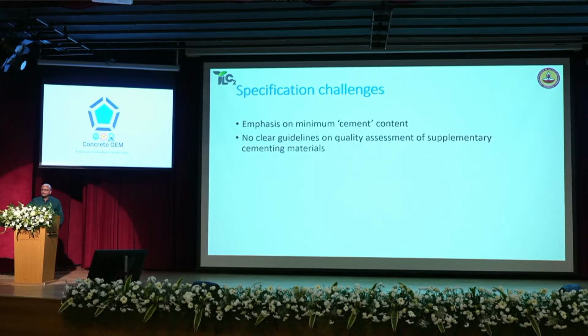There is no clear guideline on quality assessment of SCM, supplementary cementing materials. That is one of the problems why people have not been able to adopt SCMs as much as they should be, because very often the fly ashes that get supplied to ready-mix concrete do not have the right quality. And oftentimes the people who are supplying the fly ash do not ensure that the quality and the consistency of this fly ash is maintained from batch to batch. If you go to Western countries like the US, fly ash is available like a commodity product, like cement. You can buy bags of fly ash, and you can guarantee that these fly ashes are satisfying a certain physical and chemical performance. And that really helps to push the case for regulating some of these materials to ensure that they're used in a better fashion.